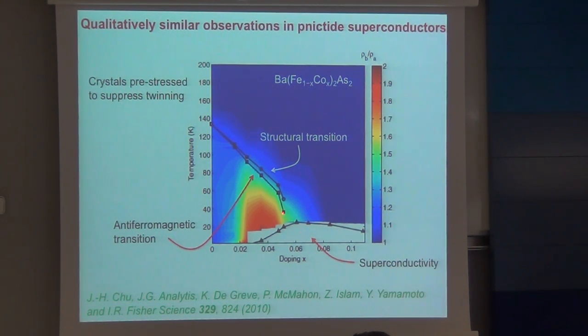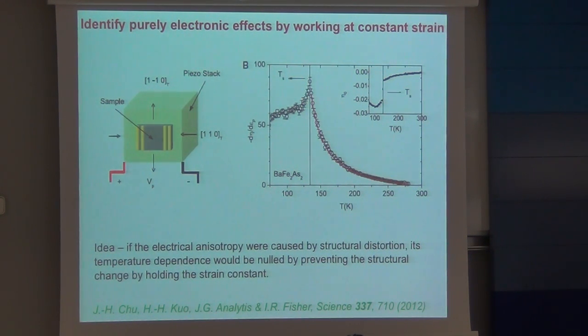But when you study the map of the anisotropy and you compare it to the anisotropies associated with these transitions, you see that it's peaked in the wrong part of the phase diagram. So in this case, the material should be getting more crystallographically orthorhombic as you go down to low temperatures and low dopings, but the anisotropy is getting more isotropic electronically. So that caused Fisher's group to postulate that you had something going on from the electronic system that was driving the strong anisotropy that you were seeing here. But of course, this is all a bit messy. You know, you can get into many arguments at conferences making statements like that in the presence of structures which aren't really tetragonal. So I think then, though, that Ian did a very smart experiment which increased the credibility of the whole thing a lot.